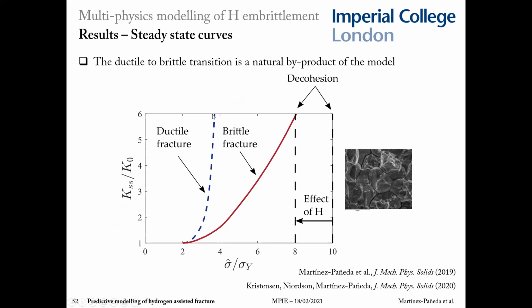So brittle interfaces will not fail. So you have a ductile fracture process. However, when hydrogen comes into the picture, it reduces the toughness, and consequently the fracture process zone, leading to the red curve shown in the figure. And you can see that this is enough to predict the brittle fracture of interfaces once you take into consideration the small reduction in strength that you get with hydrogen content, as we see in the atomistic calculations.